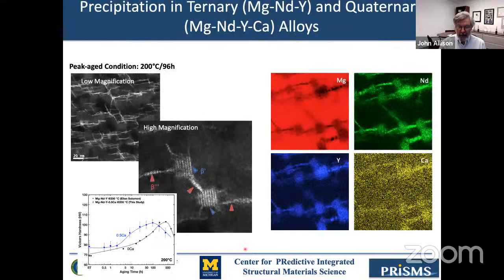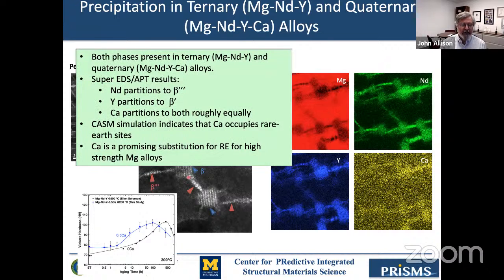We've also extended this now because, as we said, one of our goals is to understand alloying. So looking at ternary and then quaternary alloys, we could determine that, in fact, yes, yttrium segregates to the beta prime alloys. Here's some high-res TEM of Shenyang Xia in the center. And the beta triple prime, neodymium segregates to this, although there's elements of it present in both, obviously, but also calcium segregates equally between beta triple prime and beta prime. And this was also predicted by CASM that indicates that calcium occupies rare earth sites. And in addition, the calcium tended to accelerate aging. So we look at calcium as a promising alloying element and at least a partial substitute for some of the neodymium elements.